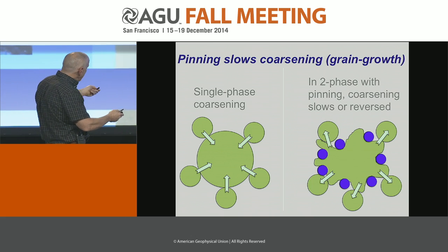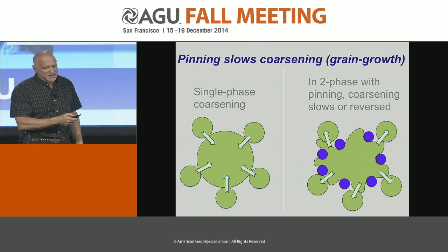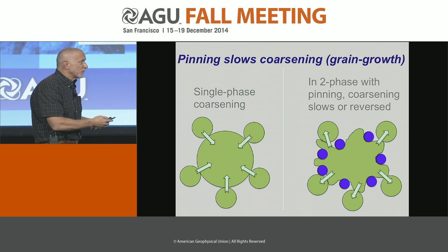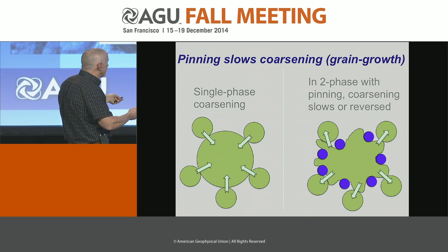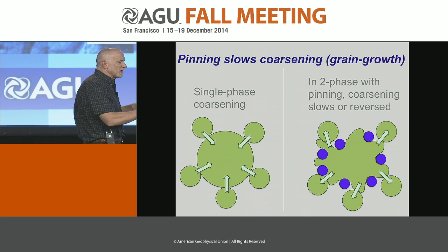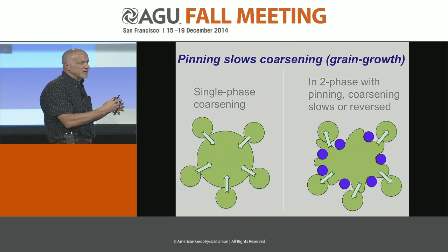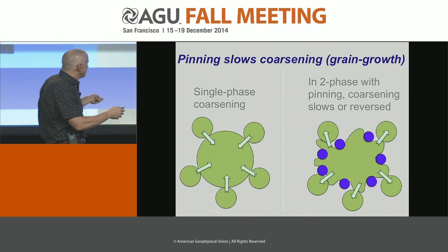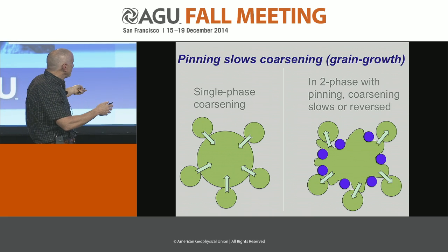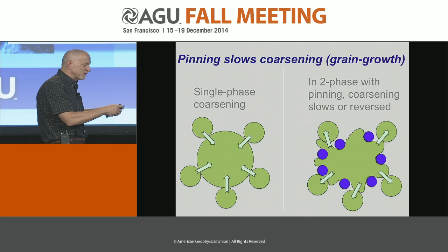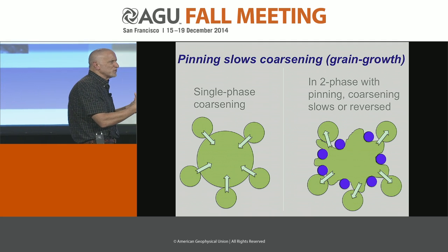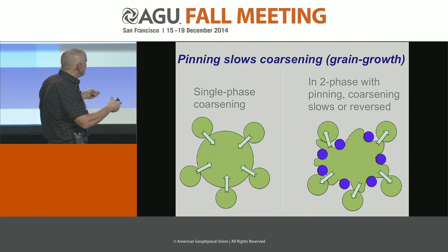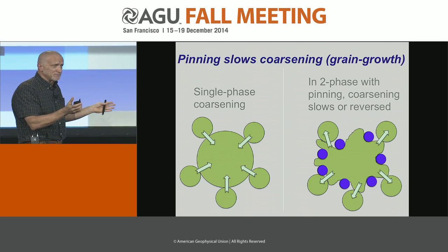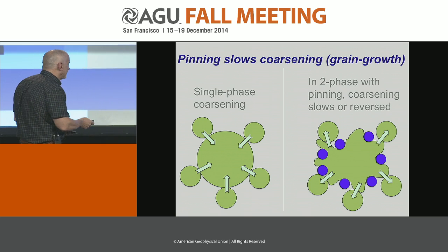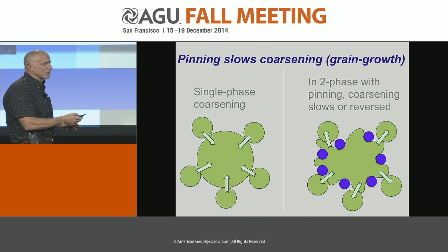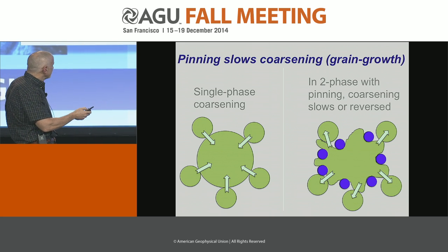If I jam pinning bodies, like these little pyroxenes, onto the boundary of the larger grain, it tends to preferentially distort the bigger grain because it fits on it. You can cause so much distortion and higher surface energy on it that you can reverse the direction of flow, because this is basically making the big grain look like a smaller grain by creating so much curvature in it, it's being squeezed more, and drive the direction of flow in the opposite direction, or stop it altogether. If you stop it altogether, that's called pinning, where you have shut down any grain growth whatsoever. And that's a very simple version of things.